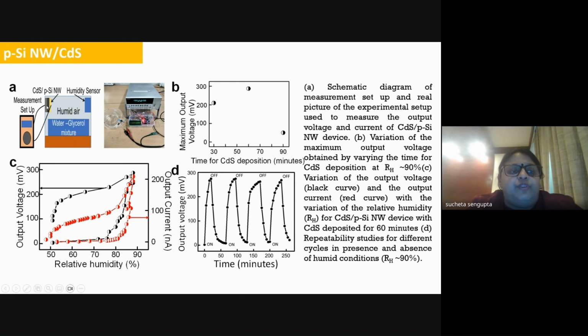We saw there is a voltage generated across this PN junction, and we tried to measure the voltage and the current which is generated. What we saw is that with the change in the relative humidity, there is a buildup of this output voltage and also the output current, and they are found to be quite reversible. That is, if you switch it on, they achieve a very high value, and if you switch it off, they retain back their original value.